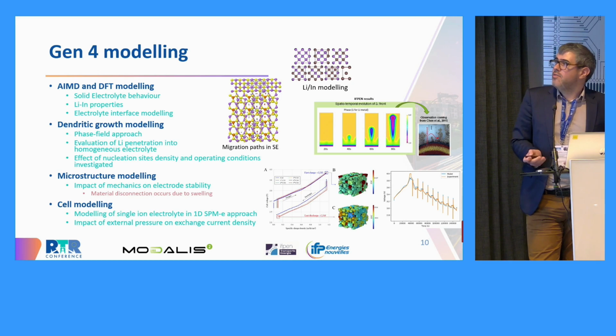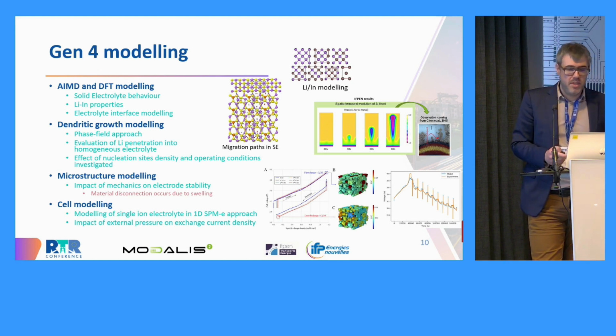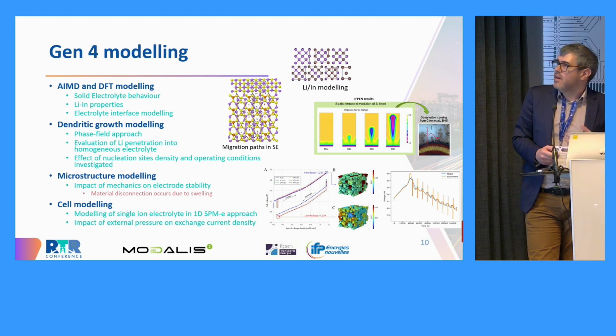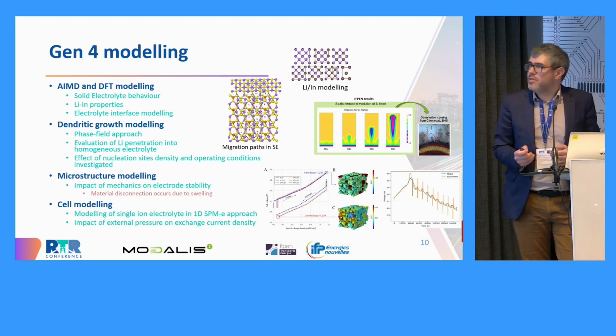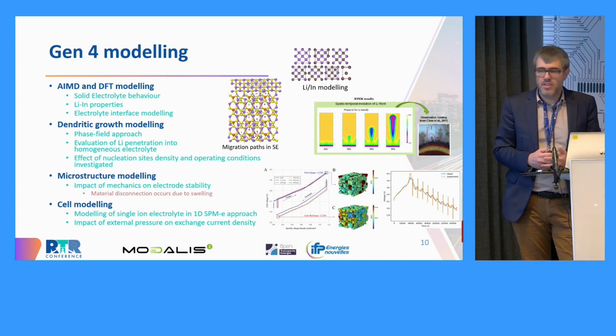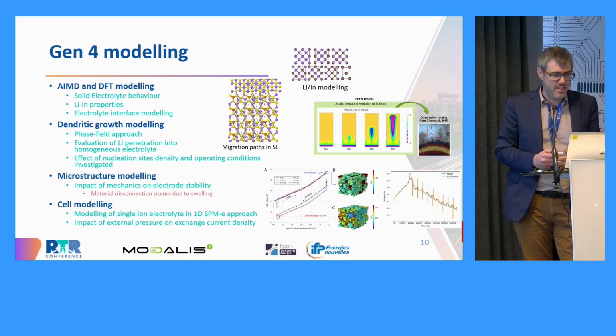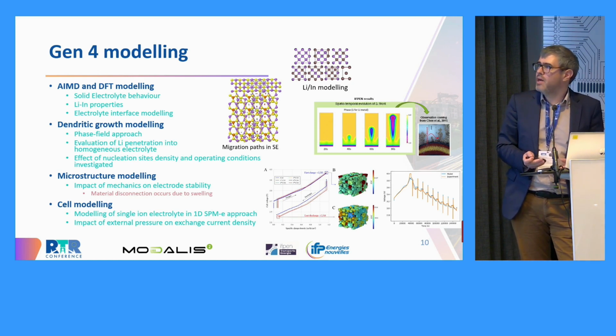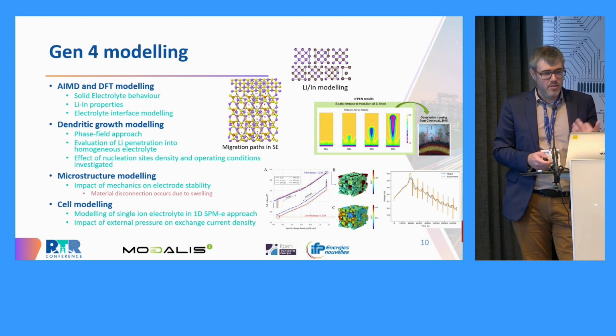Then we did a phase field model in order to evaluate the behavior of the electrolyte and how stable it was in terms of lithium argyrodite interfaces. So we were able to build this model in order to evaluate the dendritic growth in this material.